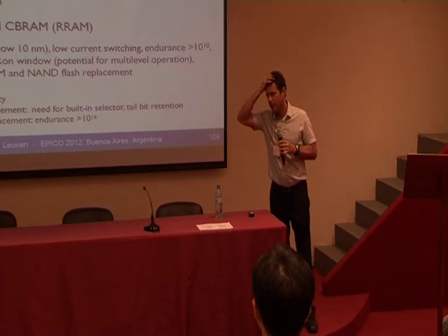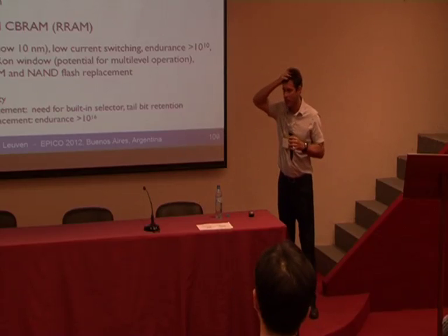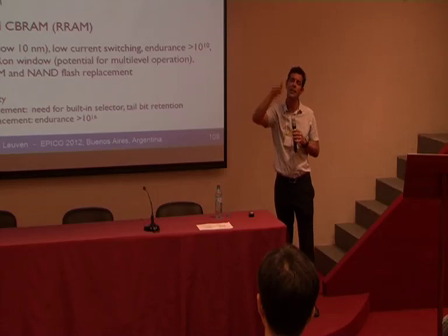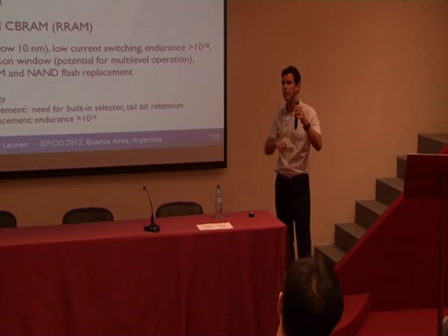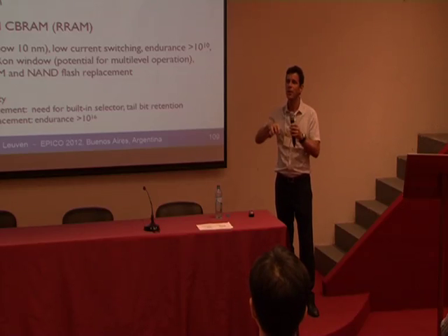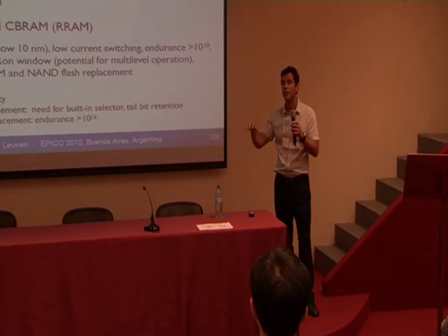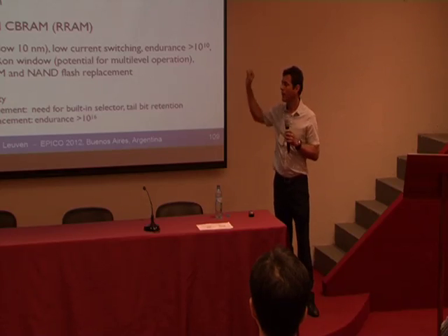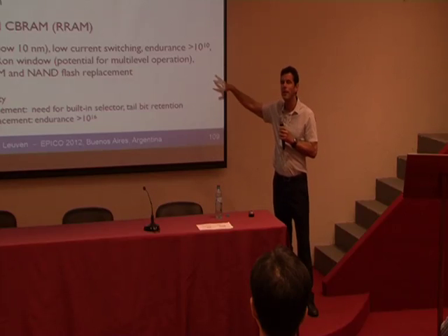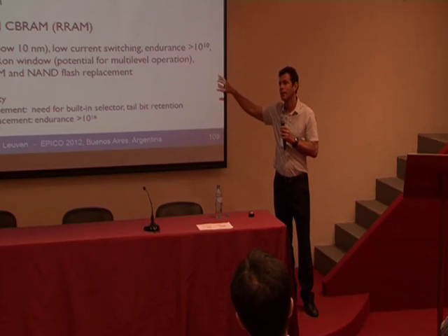So there are some papers, some people that do extremely fast measurements, where they do maybe a femtosecond irradiation or whatever, and they measure different characteristics. They say, we can see that the electronic transition precedes the heating, or whatever. So when you put a lot of energy into a system before it thermalizes, a lot of things can happen. I don't say that that's wrong. But the amount of energy you have is enough after thermalization to get above this temperature. So for our application side, it doesn't make a big difference.